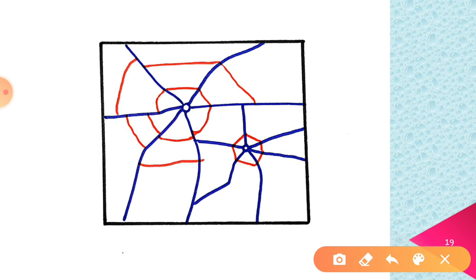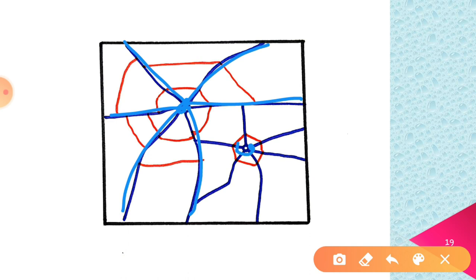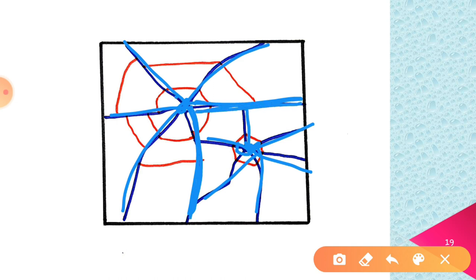Now here is an image with which you can easily determine the sequence of holes. If you imagine that this is the first hole and this is the second hole — you can see that in this first hole, the radial fractures are reaching to the end of the glass sheet, but in the second hole, the radial fractures are restricted by the radial fractures of the first one. In this case, you can easily identify that the first projectile hit the first hole in the glass sheet, and this is the second hole.